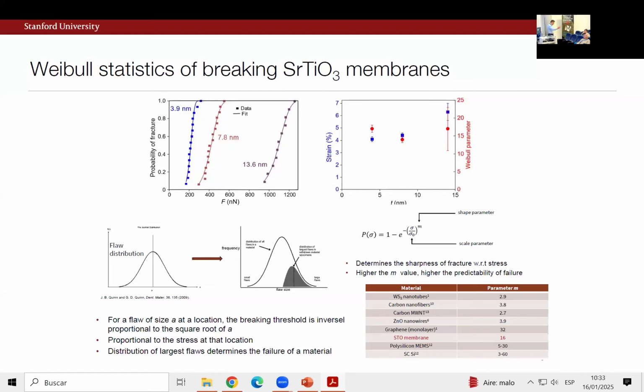So the nice thing about these hole arrays and membranes is that you have lots of holes, right? So it's not as tragic an experiment as it sounds, but literally go and break, break, break, break each one. And so this is, for example, for a 4 nanometer thick membrane. This is a measurement of the probability of fracture versus the force at fracture, right? And different thickness membranes you can pull out. Okay. So how to discuss this? We don't know microscopically what is the typical kind of defect or flaw that induces a fracture. But even without knowing that, there's been a developed set of ideas that if I have some flawed distribution in my material, it's really the extremal ones that are statistically governing when we fracture, okay?